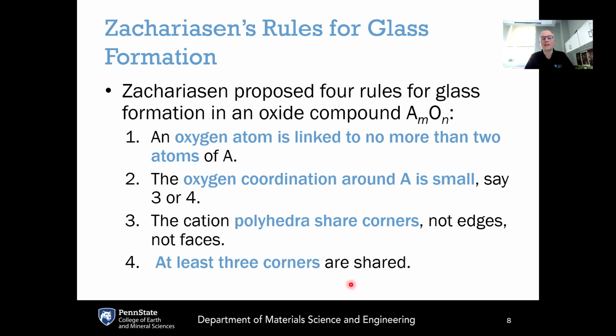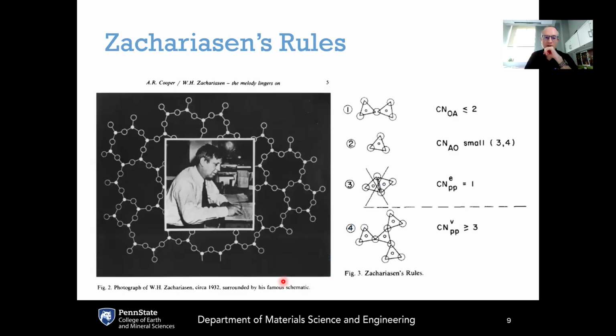And the last rule is that at least 3 corners are shared. We need to share at least 3 corners in order to build our glass network in 3 dimensions to make sure that the glass can exist and have a rigid network in 3 dimensions. So putting these rules together, the first 2 rules define what is the basic structural unit in terms of how the oxygens are coordinated around the cations and how the cations are coordinated around the oxygens. Once we've defined the basic structural unit, they're connected to each other through corners, and at least 3 of those corners are shared in order to build the 3-dimensional network. So these are Zachariasen's 4 rules. Make sure that you know each of these rules.